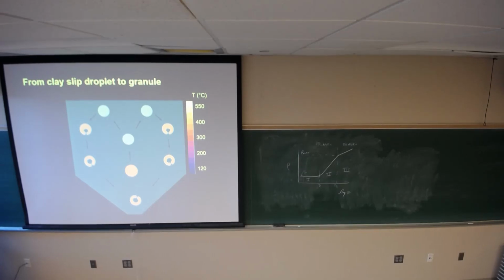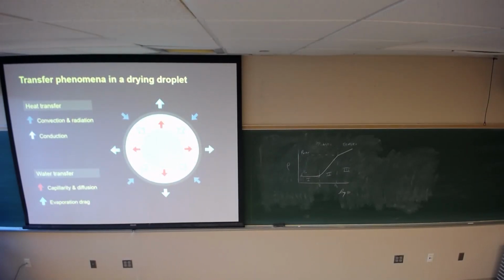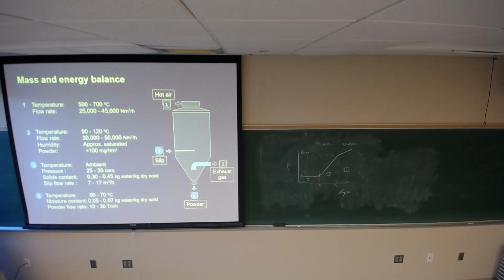I'm going to skip this and come back to it on Friday when we meet again. Okay, these are the numbers I'm going to leave you with. Number 4, powder out, flow rate 10 to 30 metric tons per hour is what they're producing for granulate. Staggeringly large. Right? And then what you're bringing in basically is 25 to 45 cubic meters per hour of slip,